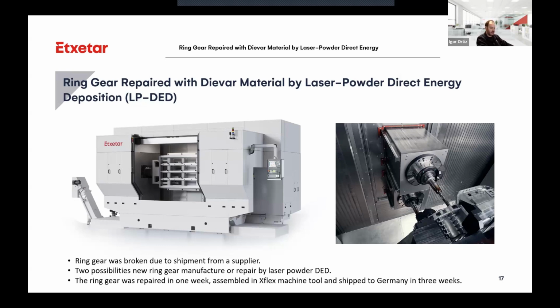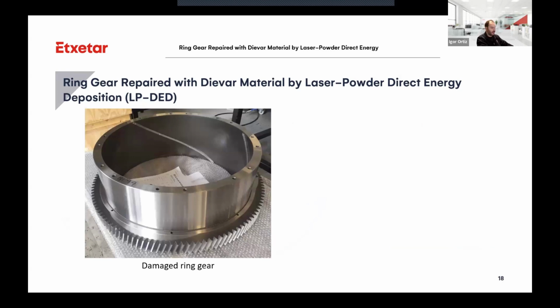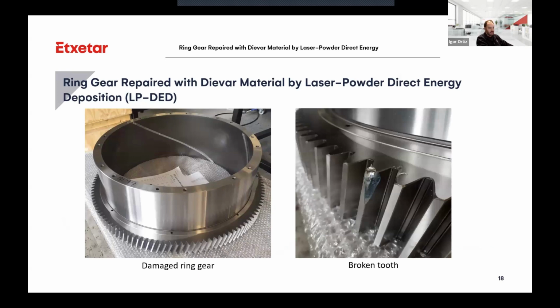Internally, Etxetar told us to repair by laser powder direct energy deposition. So we take the gear, because this gear or this machine tool has to be shipped to Germany in 3 weeks. This is the damaged ring gear. I can't show the drawing, but the dimensions are between 700 and 800 millimeters in diameter. This is a broken tooth that it has, for example, in the gears, due to the shipment, that has been broken.